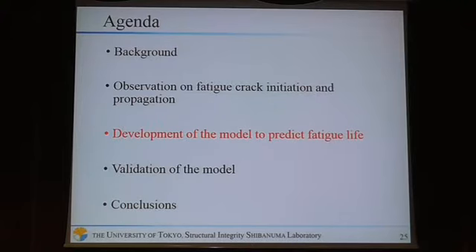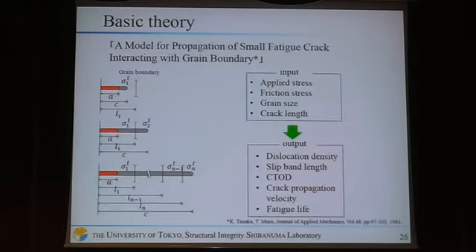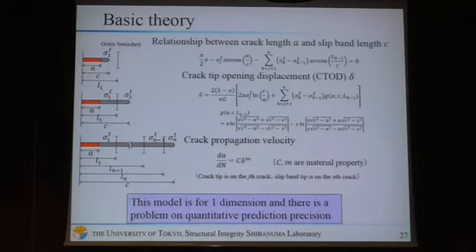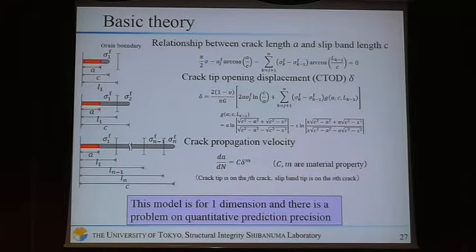Next, the development of a model to predict fatigue life. This study is based on a theory, a model for propagation of small fatigue cracks interacting with grain boundaries. This theory needs 4 input parameters to calculate fatigue cracks. CTOD value is calculated from this formulation, and crack propagation velocity is calculated from this formulation. However, this model is one-dimensional, and there is a problem with quantitative prediction precision.